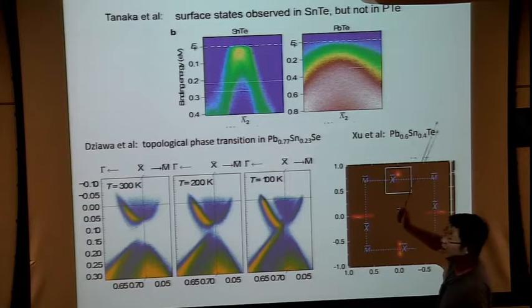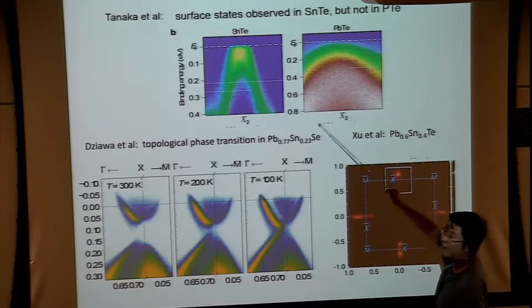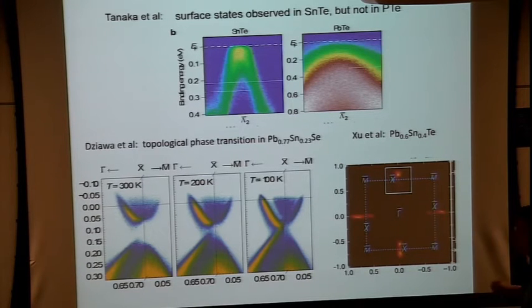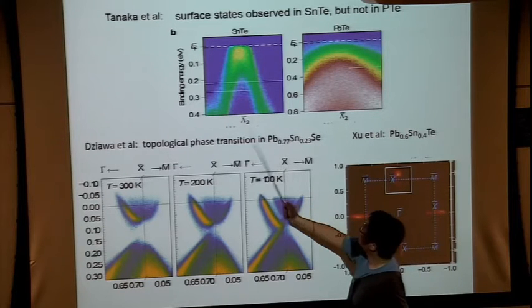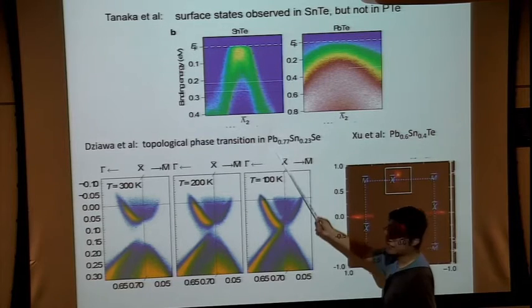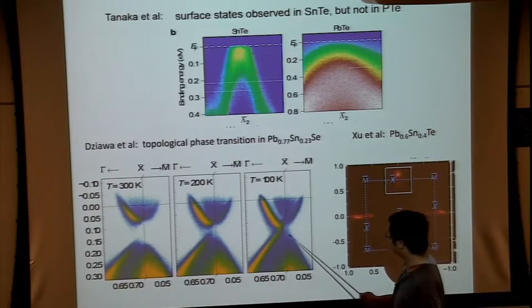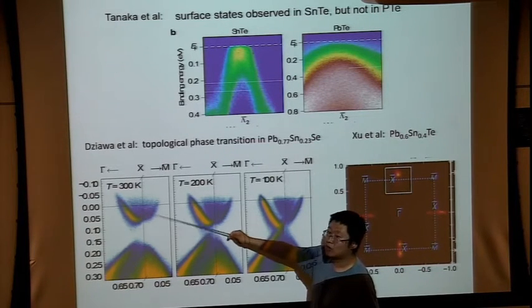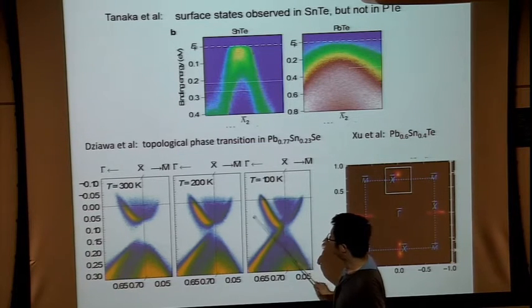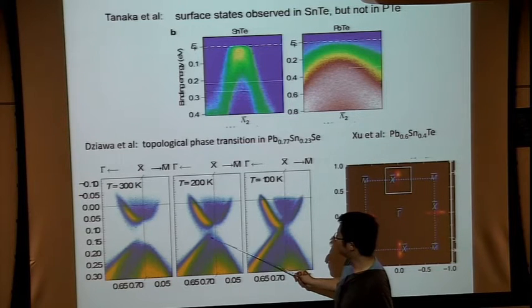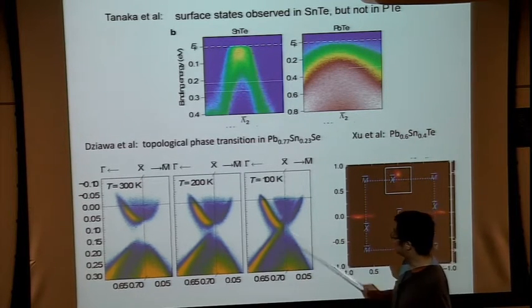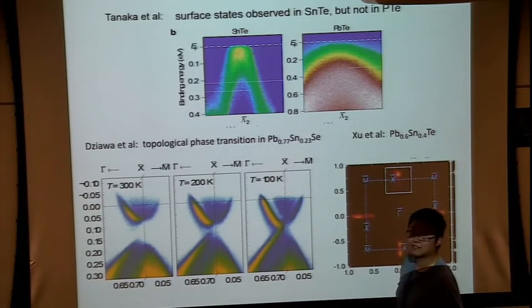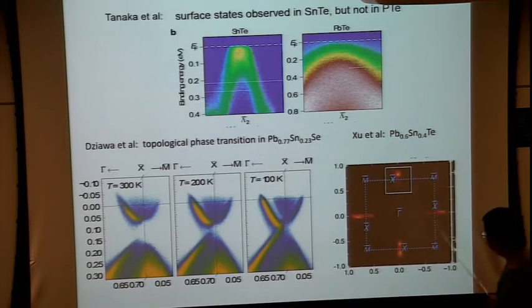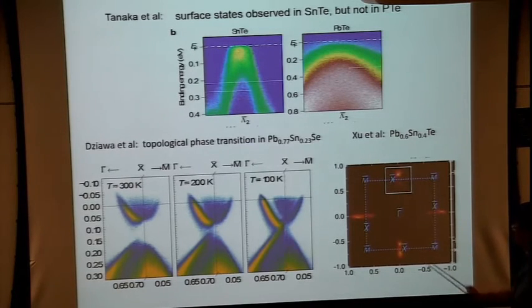Yoichi Ando's group in Japan studied both compounds, lead telluride and tin telluride, by photoemission, and you see that lead telluride has a gapped surface state. Tin telluride has this predicted Dirac surface states, which is away from the X point. Okay, so this one is away from the X point. And very interestingly, in this related compound, lead tin selenide, at high temperature, the band gap is normal with no surface states. But as you lower the temperature, the bulk band structure changes. The bulk band gap decreases and then goes through a band inversion as a function of temperature. So at low temperature with inverted band gaps, you see that again the Dirac surface states appear, again away from the X point. Right. So from Hasan's group, you look at photoemission, and in the entire Brillouin zone, the 001 surface has these four Dirac cones.